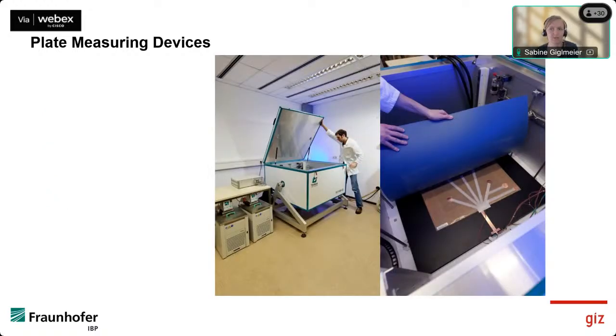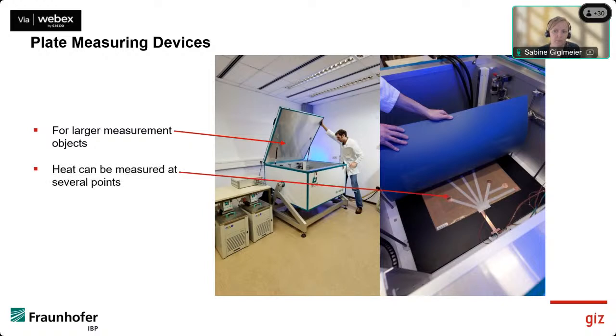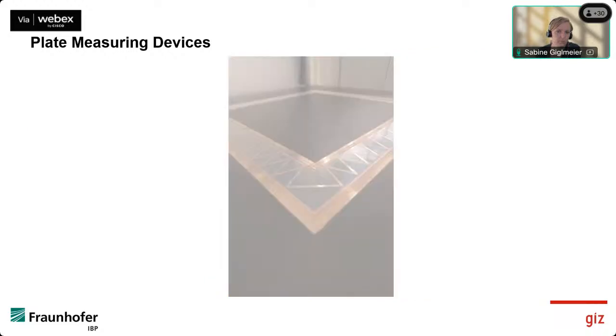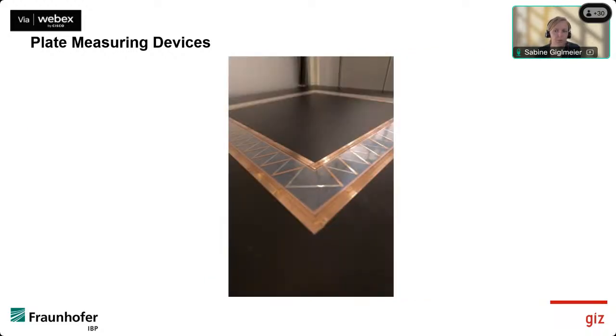These devices come in different variants and they differ in the dimensions of the samples possible to be measured within, but also in the temperature range and angle in which measurements can be performed. In this picture you can see one example device which is capable of measuring composite materials as we have seen earlier, but is also capable of being tilted. Inside the device, different modules are installed. These make sure that the heat flow runs always vertically through the sample, even if the device is tilted. This is needed so that the measured heat flow gives only the heat flow through the sample. This has to be true even if the measuring is not made vertically but tilted, for example due to measurement of pitched roof components.